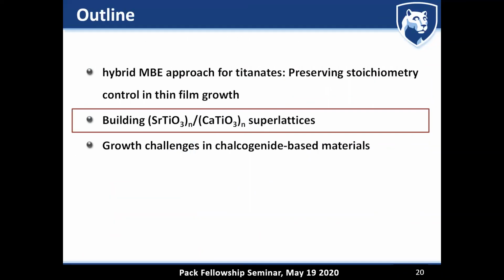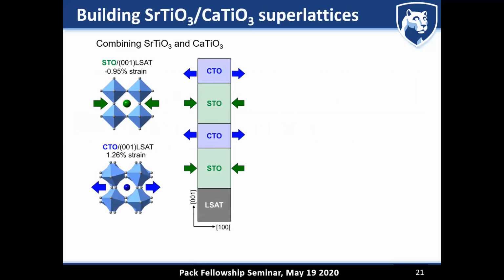Now, if you take this, you can actually go one step further. So far, I've just limited this discussion to what I would call relatively thick films, but you should be able to scale this down now. And so the second step was trying to grow superlattices, ideally superlattices of two materials, in this case, strontium titanate and calcium titanate. This really hits home this point that we have the same structural motif. We should be able to epitaxially integrate them. And the idea is to basically grow a stack of strontium titanate and calcium titanate, and then repeat this. It turns out that given the lattice parameters of strontium titanate and calcium titanate, the strontium titanate would be compressively strained while the calcium titanate would be tensile strained. So we should get some very interesting domain structures in the ferroelectric state.